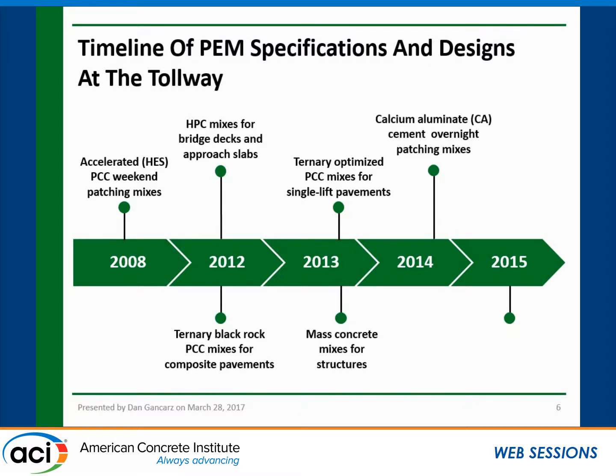And then as the Move Illinois Capital Program was getting underway, specs were developed for HPC mix designs used in bridge decks and approach slabs, and then also ternary black rock mixes for composite pavements. And when I refer to black rock, it is coarse, reclaimed asphalt pavement that is used as a replacement for a portion of the coarse aggregate, and it fits in more as an intermediate coarse aggregate. And then in 2013, we developed ternary optimized mixes for single lift pavements that were used on the eastern end of I-90. We also developed a performance spec for mass concrete.